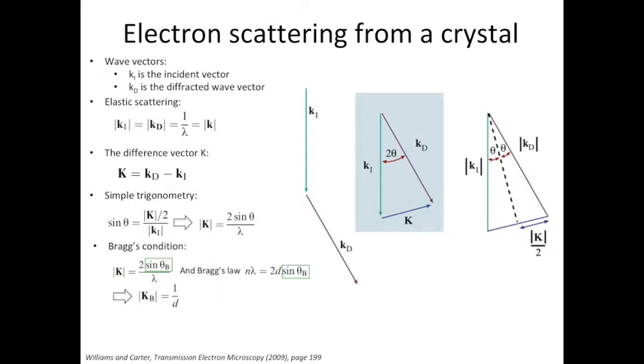Another thing worth noting is that as d increases, the kb value decreases. So in real space, if the lattice parameter or the lattice spacing increases, then the value of kb decreases in the reciprocal space. We define the vector kb as g, and kb is also called the g vector. You will encounter the term g vector many times in diffraction, as well as in the imaging section of this course.